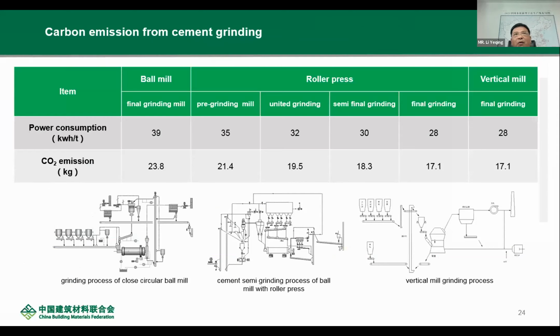As for the cement grinding system, the power consumption for the traditional ball mill is 39 kilowatt hours, and the carbon emissions is 24. Now we use a roller press plus ball mill system, including pre-grinding and united grinding and final grinding system. The consumption can be reduced from 23 to 18. We also have the vertical roller mill as a separate final grinding system. The carbon emissions are very low, only 17. Overall, between the ball mill and the vertical roller mill system, the difference in carbon emissions is only 6 to 7 kilograms. Considering the total cement carbon emissions amount, the difference is very limited. So the biggest impact is the fuel.